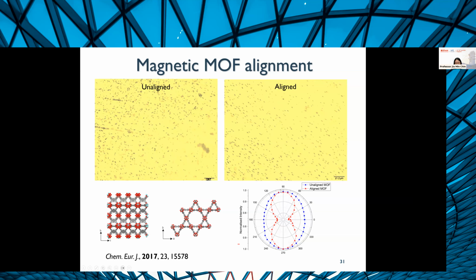These particles don't have as high an aspect ratio as the MIL-53, so the alignment is not quite as easy to see. But we saw that if you shine linearly polarized light along the longer axis of these MOFs, they have an anisotropic fluorescence response. NU-1000 has these pyrene-type linkers, and these are fluorescent moieties. So if you shine the light in this direction, we get the maximum fluorescence response, versus if we shine the light perpendicular to the MOF crystals. And of course, in the unaligned MOF, you don't get a directional response as such.